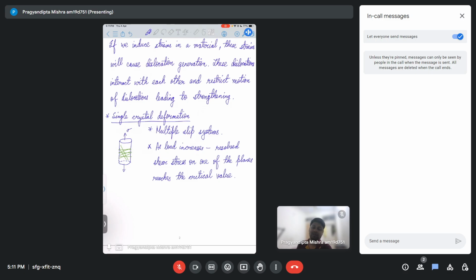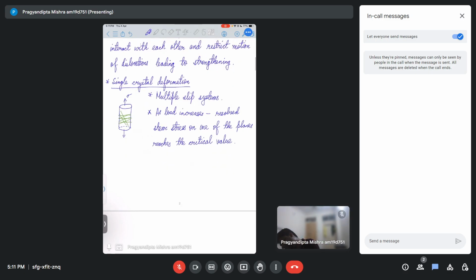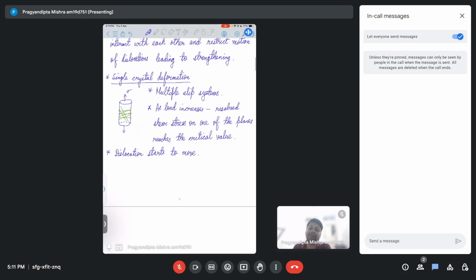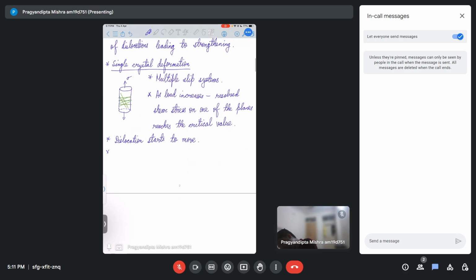So now what happens? Once one of the resolved shear stresses has reached the critical value, then dislocation will start to move in that particular slip plane, right? So dislocation has now started to move in that particular slip plane. It has reached the critical value, dislocation gets generated, it has started to move. Now what will happen? The load will keep increasing. Over time, CRSS on other slip systems will also be reached. So other slip planes, other slip systems, will also get activated.